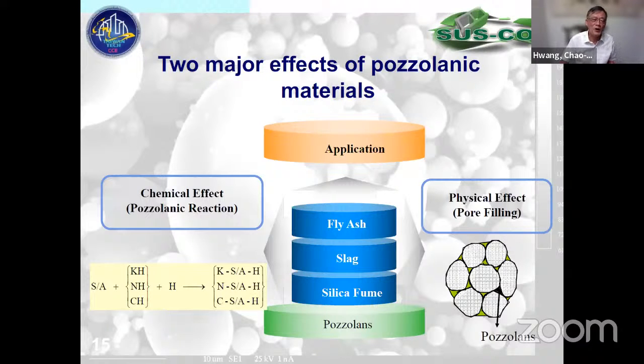By looking at the chemical effect on the left-hand side, the fly ash or bottom ash, by adding calcium hydroxide, sodium hydroxide, and the concrete cement, calcium hydroxide, and adding some water, drives the reaction so they can form a lot of gel and crystal. So that's the reason concrete can last longer, because of the reaction. So what we are doing, next please.